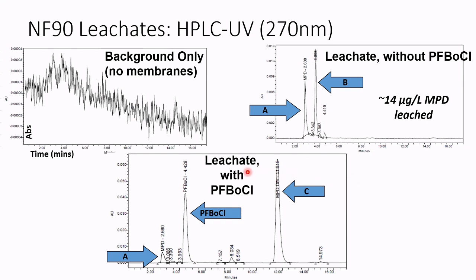So then when we derivatize that sample with the pentafluorobenzoyl chloride, you'll notice that there are 2 new peaks that emerge. There's one here, which is the excess pentafluorobenzoyl chloride. That's what we added, so we're not interested in that peak. But there's a peak right here. And this peak at 12 minutes suggests that whatever was coming off of the membranes is now tagged.